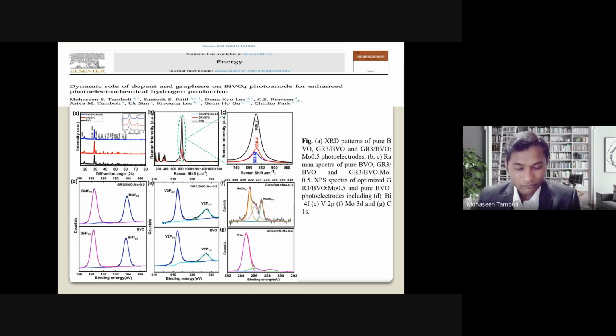The graphene molybdenum photoelectrode exhibits similar peaks to the bismuth, vanadium, and oxygen spectra. We observed the same peaks in the Raman as well, but when we check the XPS, a shift can be observed. Here you can see BiVO4 and BiVO4 graphene molybdenum. A small shift is observed on the lower side, showing molybdenum doping in the composites. The same thing we observed in figure E for vanadium, where a little peak shift is also observed. Figure F is molybdenum, and figure G is carbon. We have used graphene here, so carbon is showing.